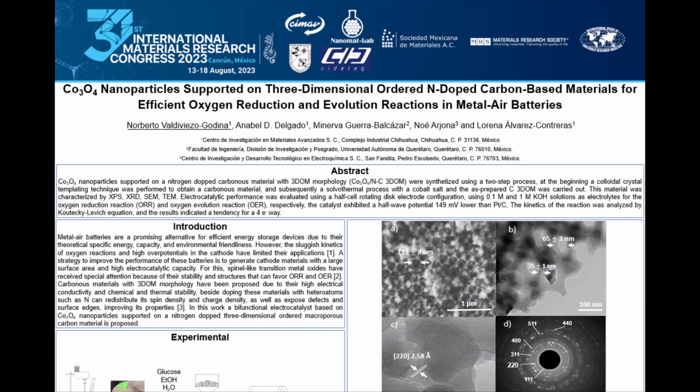Cobalt oxide nanoparticles supported on three-dimensional ordered nitrogen-doped carbon materials for efficient oxygen reduction and evolution reactions in metal-air batteries. These batteries have emerged as a promising alternative for efficient energy storage devices, and using defect engineering strategies such as doping carbon structure with heteroatoms like nitrogen can improve the general performance of these batteries. Because of this, in this work, a bifunctional electrocatalyst based on cobalt oxide nanoparticles supported on a nitrogen-doped three-dimensional ordered microporous carbon material is proposed.